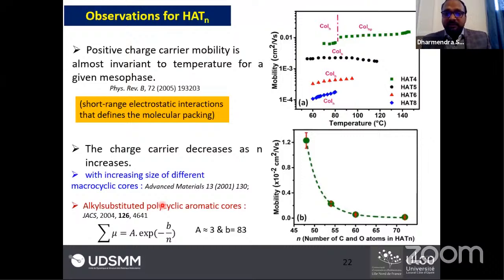Here there was a little discussion about the charge carrier mobility as a function of temperature. Basically, triphenylene-based compounds show a temperature-invariant charge mobility. Depending on the alkyl chain length, the mobility reduces, but over temperature it is almost constant. So why does mobility decrease from the HAT4 compound to the HAT8 compound? This is due to the short range electrostatic interactions. These short range electrostatic interactions basically explain the molecular packing. So when molecular packing or molecular ordering reduces, the charge carrier mobility also reduces.